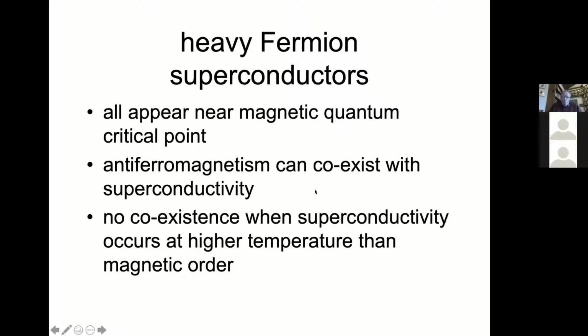Another point that I'll discuss has to do with the fact that antiferromagnetism can coexist with the superconductivity. But in instances where, using a variable such as pressure, you have a magnetic transition curve and a superconducting transition curve crossing, if superconductivity occurs first, in other words at a higher temperature, you do not have a lower temperature magnetically ordered phase. And this to me is a rather important point.